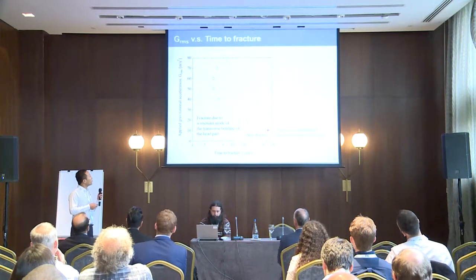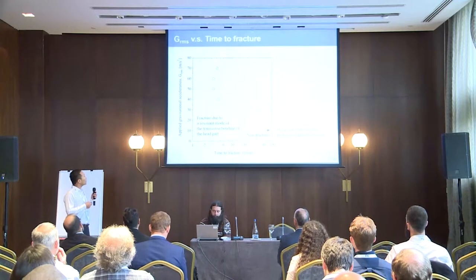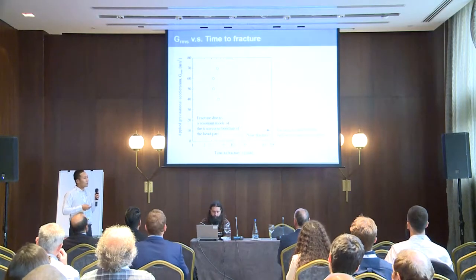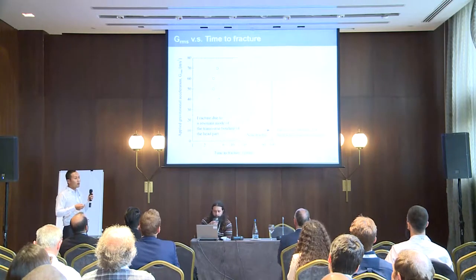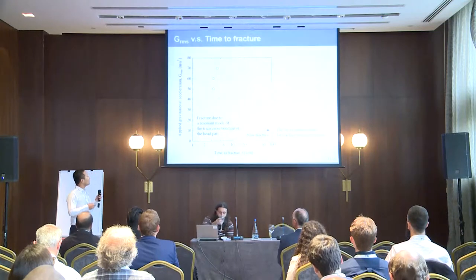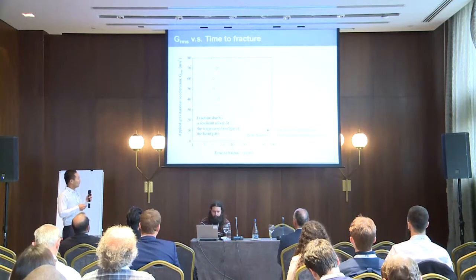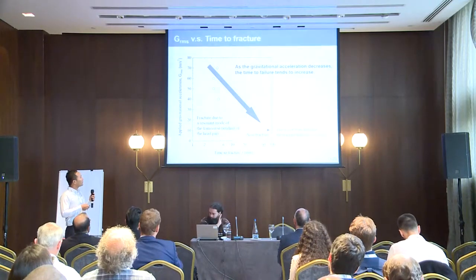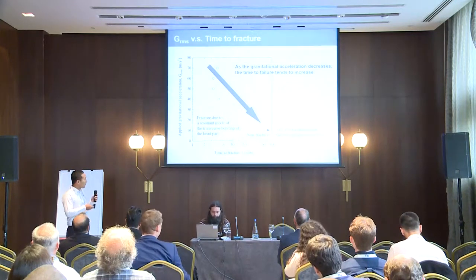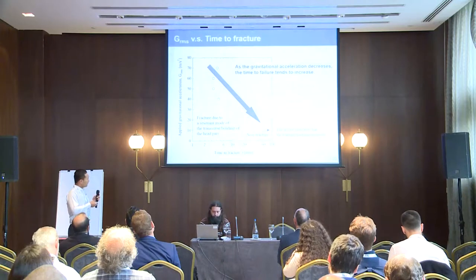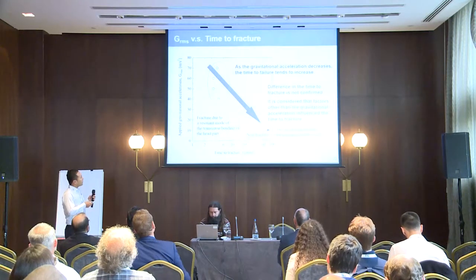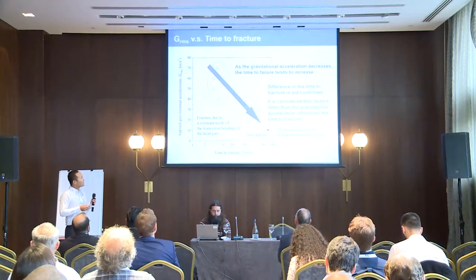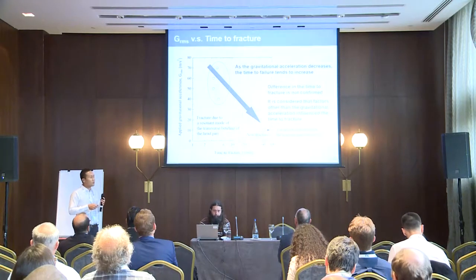This figure shows the relationship between the applied gravitational acceleration and time to fracture. The arrow indicates that fracture had not occurred within one hour. We observed the vibration test and considered that fracture could occur due to the resonant mode of the transverse bending of the head part. As the gravitational acceleration decreases, the time to failure roughly tends to increase. However, in some areas the difference in time to fracture is not significant, suggesting factors other than gravitational acceleration also influence the time to fracture.